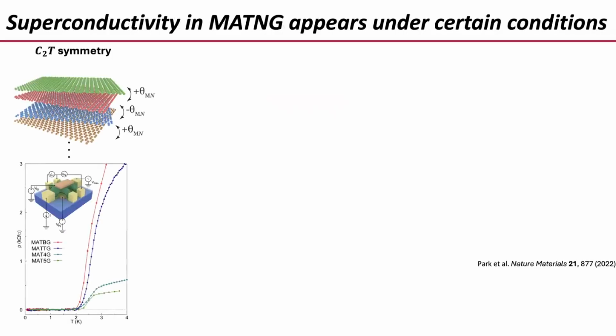So superconductivity in magic angle twisted N layers graphene, could be bilayer, trilayer, tetralayer, appears under certain conditions. And since we have a lot of tunability, we have narrowed down these conditions quite well. For example, it seems to appear or be most robust, strongest in systems which have C2T symmetry, okay? And at least all of the systems that have the C2T symmetry exhibit this superconductivity, and very robust.